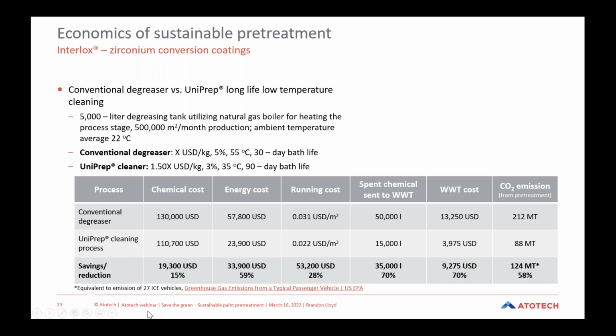Then if we looked at the running cost, which is in the third column here, you can see that if we look at the conventional degreaser, it has a running cost of about 0.031 US dollars per square meter. And with the Uniprep cleaning system, we're able to reduce that by about 53,000 US dollars, which is the summation of the chemical and energy costs, which is a total reduction of about 28% for the applicator. When we look at the spent chemical sent to wastewater treatment, this is coming exclusively from the extension of bath life. Here we can see that we're able to reduce that by about 70%. And then the associated costs by reducing that wastewater treatment burden is about 70%, or about 10,000 US dollars.